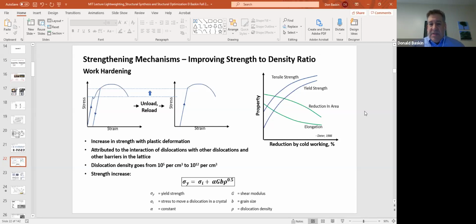The reason this happens is because of these dislocations. If you can stop them from moving, if you can get them tangled up in something else in the microstructure, like a precipitate, a little oxide that's stuck in there, you can stop these dislocations from moving, or maybe not stop them from moving, but make it so that it requires more energy to keep them moving. That's what's creating this work hardening effect.